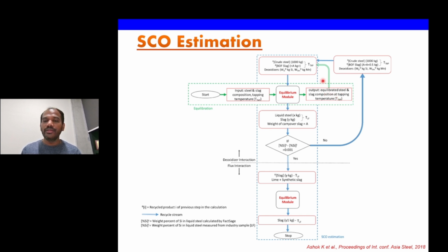Now this output, crude steel, is recycled, you can see. Then you change it to per ton of crude steel. And the BOF slag, which we do not know, right? During the tapping process, how much of the BOF slag is done, that we do not know. So you keep that as an unknown. We know that the close bracket with the A, we put it as a variable, and then deoxidizers, whatever added in the tapping process, like silicon and manganese, all these things can be given as an input again into the equilibrium module.